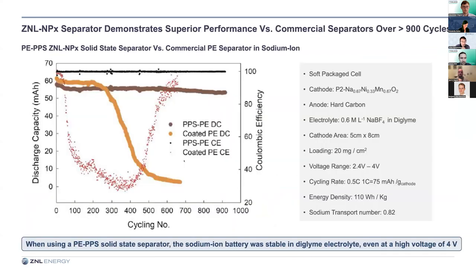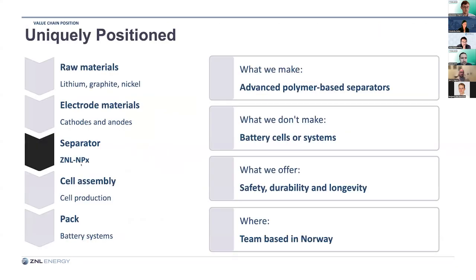We also have external tests. This is from a sodium cell with 4 volt. And you see the orange and the scattered, it's the conventional separator. With ours it's almost at 100%, and it's really, really even on the cycling. So we lasted over 900 cycles. So this is on the next level chemistry. We also see a similar test in high NMC 9XX from a US player where we doubled the lifetime of the battery.